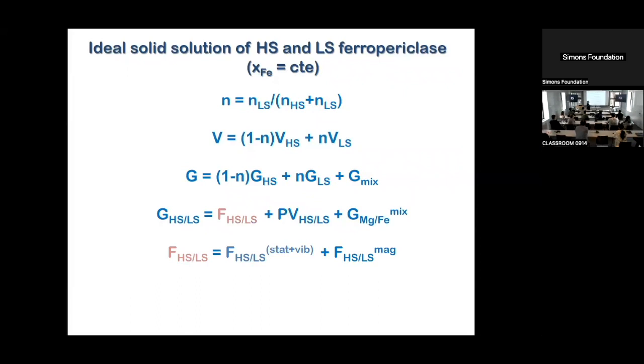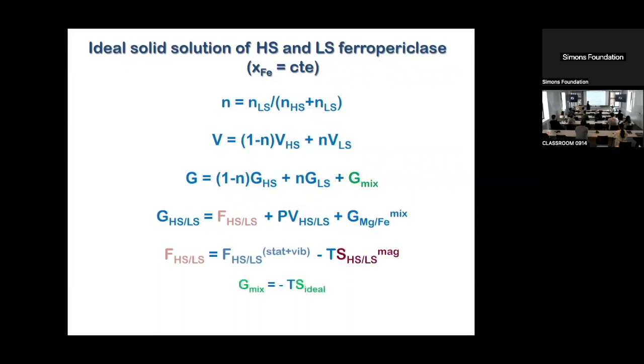It's given in the atomic limit. In other words, if you have ions with spin S, you have 2S+1 states per ion. So this is certainly something that is overestimated, and we can see what the effect of some overestimation here would be. Better models for this spin entropy would be very, very welcome.